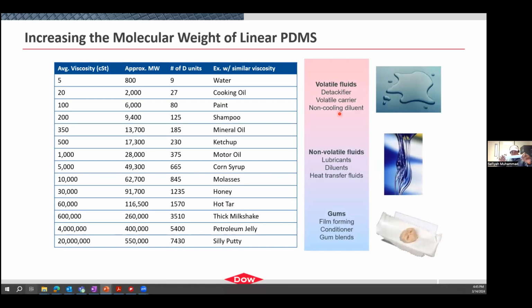So this very thick material that I have here is a silicone-based material, and it's essentially made up of a lot of PDMS chains with an extremely long number of D units. And so we can take advantage of these differences in viscosities in their final application, right? So if we think of something with a very low viscosity, it'll be a volatile fluid, so it'll evaporate over time. And so we have different applications for those types of materials.